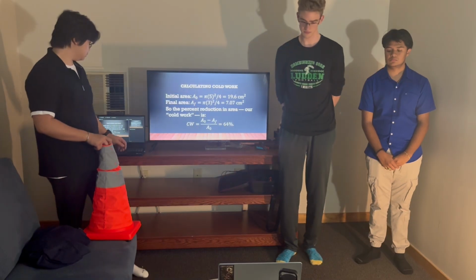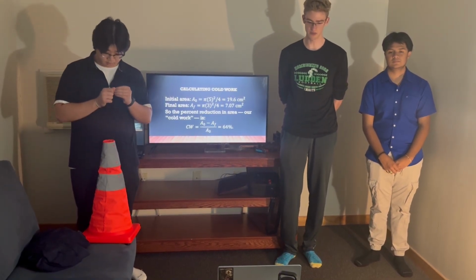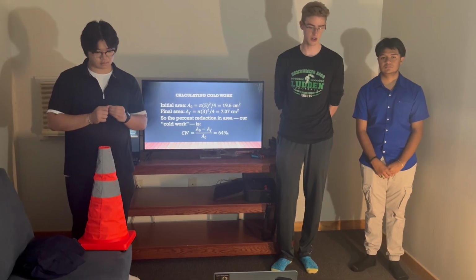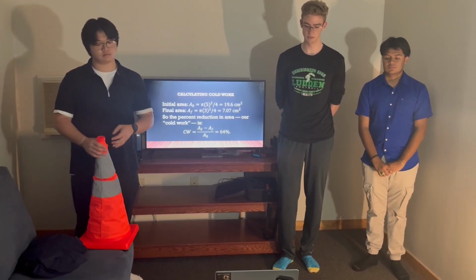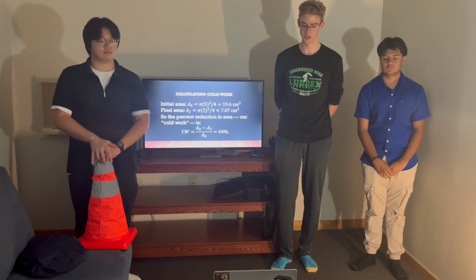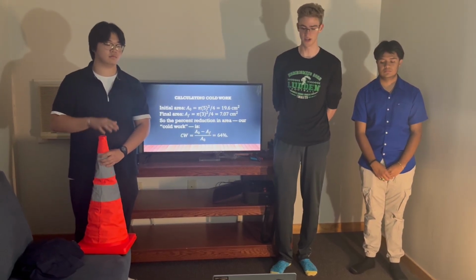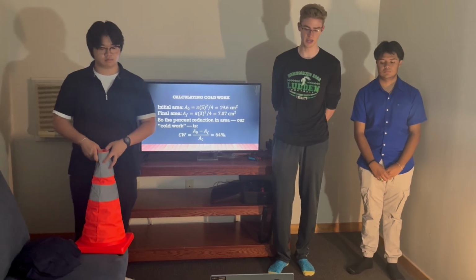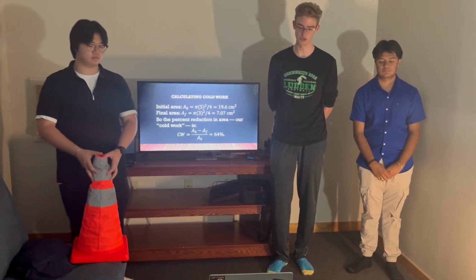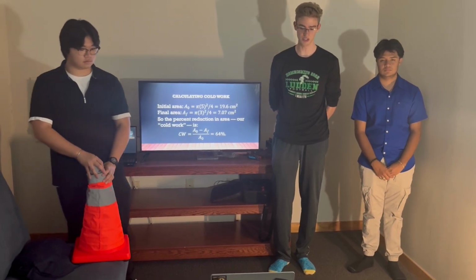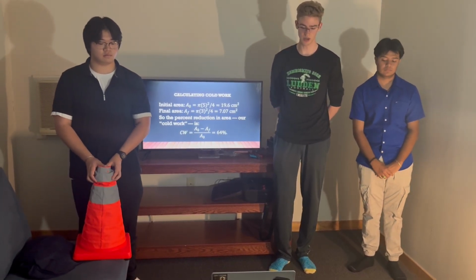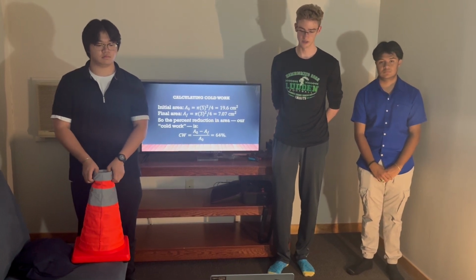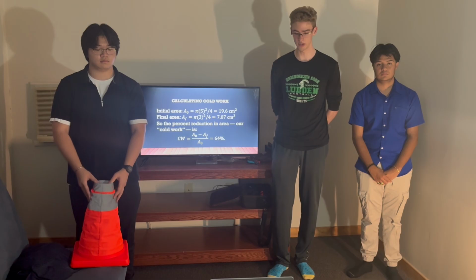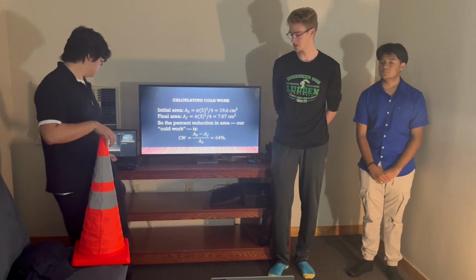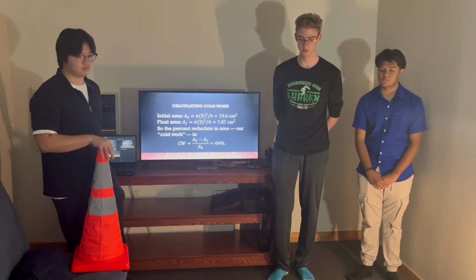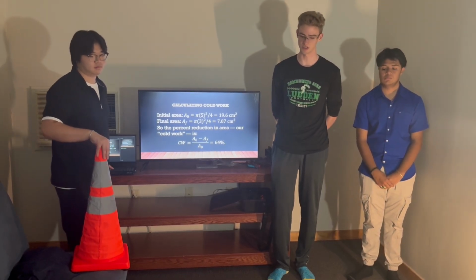over and over. The amount of cold work is based on the reduction in cross-sectional area. The initial area is found by A0 equals pi times 5 squared over 4 equaling 19.6 centimeters squared, and the final area, AF, is found by pi times 3 squared over 4 equals 7.07 centimeters squared. So the percent reduction in area, our cold work, is CW equals initial area minus final area all over initial area equals 64%. And each of those equations is simply just a plug-and-play version of the area for a circle.